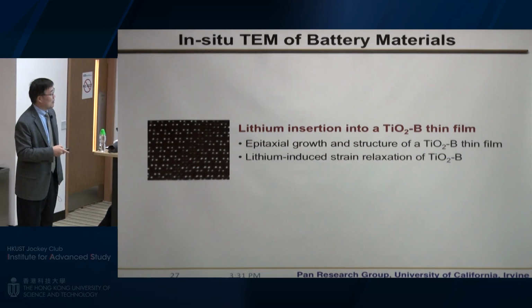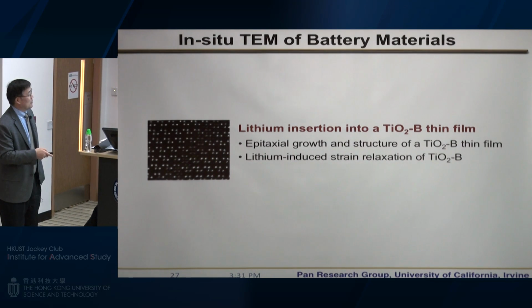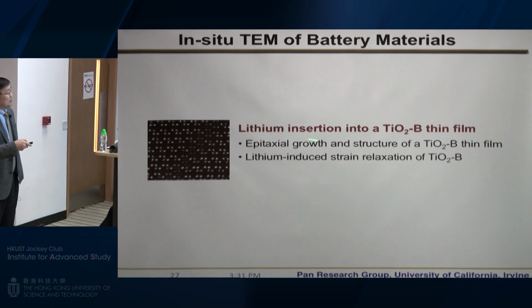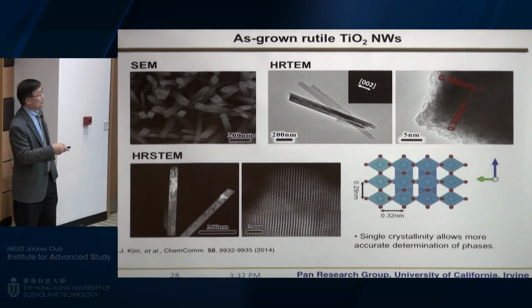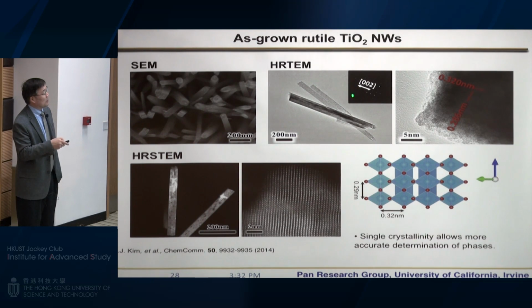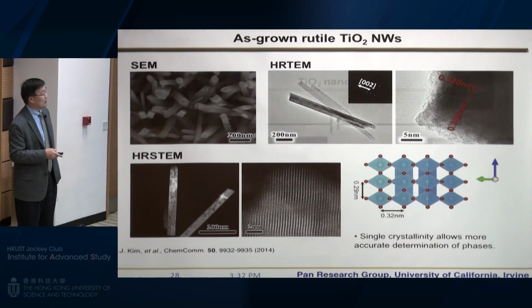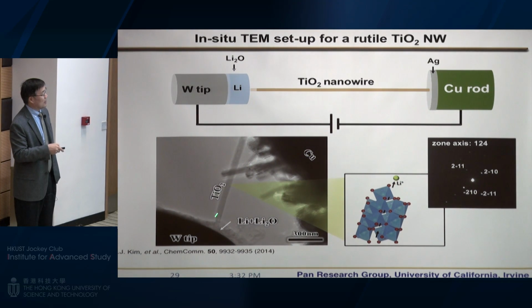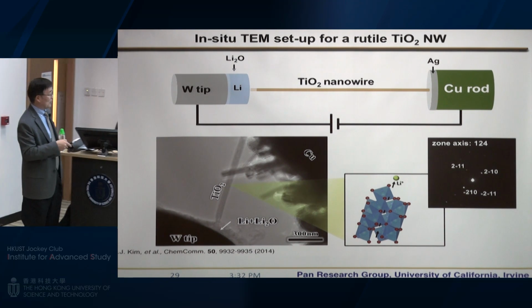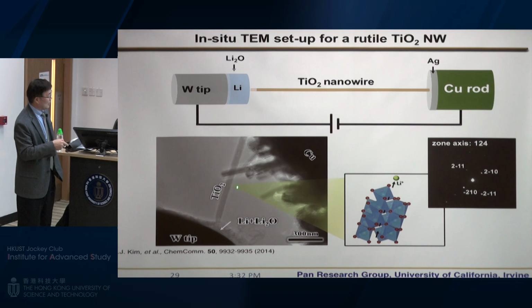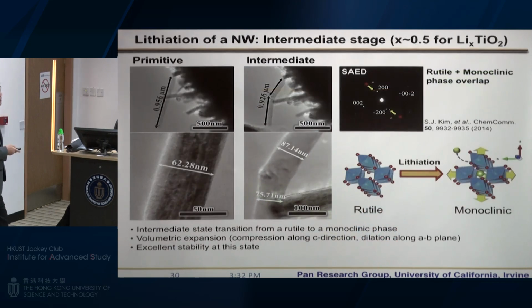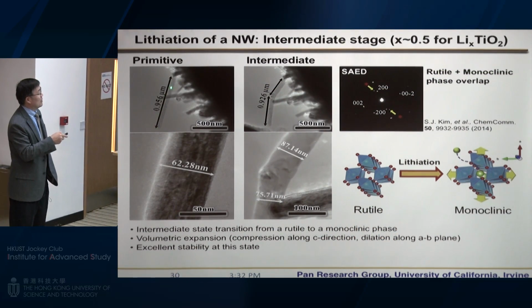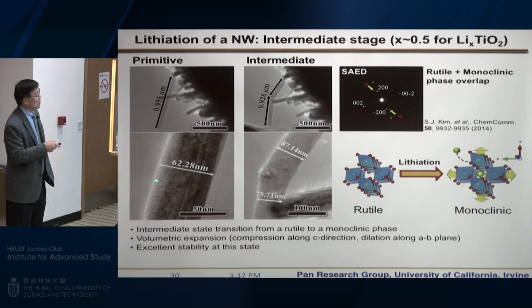So Sangju did three different material systems. I'm going to show you two: lithium insertion in TiO2. First is very quick. It's a TiO2 rutile structure, and this is a typical nanowire of TiO2. We apply an electric field, and then you will see lithium diffuse from here and gradually change the structure. The structure change has two effects. One is the diameter will expand, but the length will shrink. You can see it from here. So initially you have this length, and then shortly it becomes shorter, but much thicker.